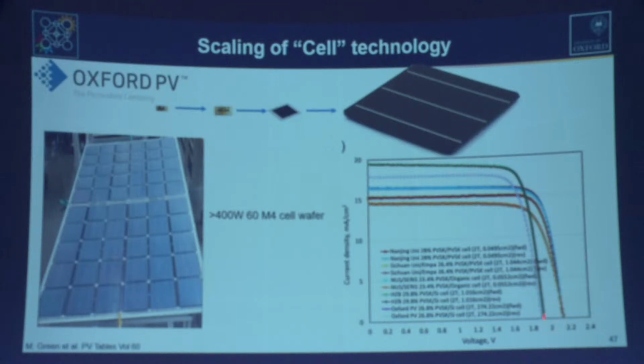What you see here is the voltage is just the same. The shape of this curve is nice and square - that's a term we call fill factor, which is really important for solar cells. It means very few resistive losses. The current's a bit down, and we know why - this is something that will be improved on the large cells.